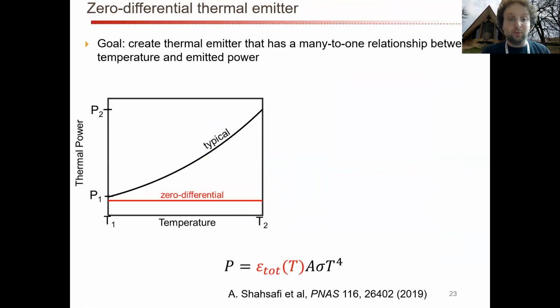So in other words, what we really needed is a thermal power versus temperature that, instead of increasing like would normally be the case, was kind of this zero differential case. The derivative was zero, and therefore you had a completely flat curve. And if you take a look at this equation, this integrated, essentially Stefan-Boltzmann law, you can see that your total emissivity needs to decrease as fast as temperature to the fourth increases to kind of cancel this out.